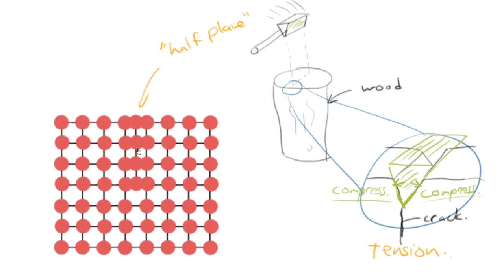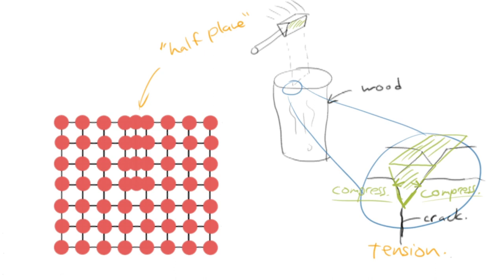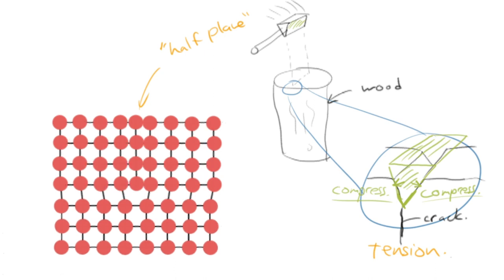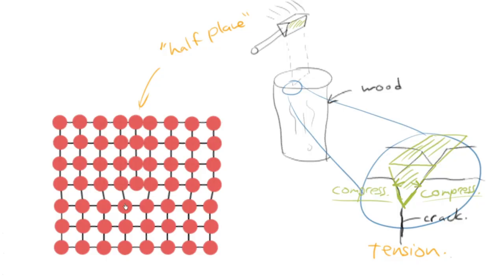Well, what it does is it takes up some space. And so I went ahead and I drew that in ahead of time. So what will happen is it pushes the lattice apart like that. It's pushing the lattice apart to take up space. And so these atoms down here are actually being pulled apart. I didn't really illustrate that entirely, but the lattice is in tension down here.